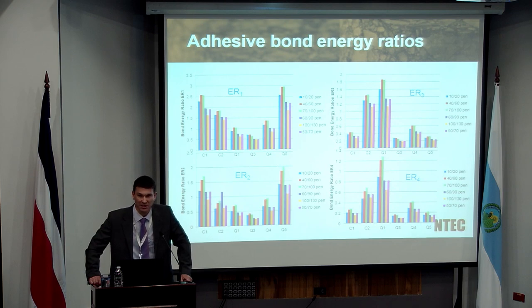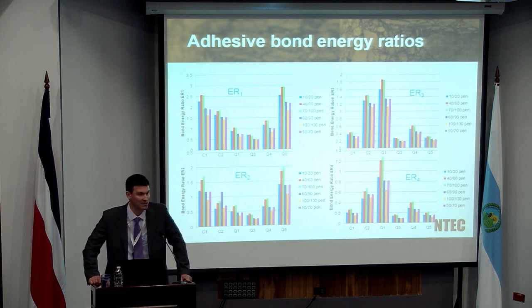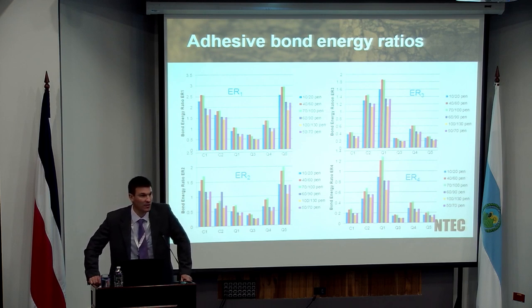Does it actually mean that the material is going to fail? No, because we are obviously still having to have the influence of water entering our pavement structure. So if we keep our pavements nice and dry, have a good waterproofing seal on the surface, make sure the drainage is adequately considered in terms of the design, then we may be able to use that material. But what the graph is telling us is that if we are concerned with water getting into our system, we would want to select a better combination in terms of those energy ratios.